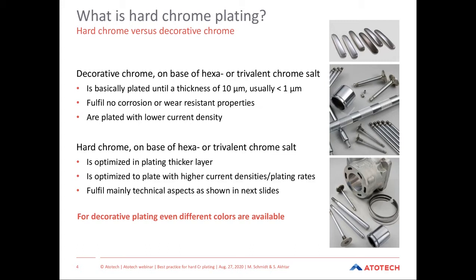Hard chrome, on the other hand, is plated to improve the lifetime of the component in service. It is usually plated to thicknesses ranging from 5 microns up to 300 microns, of course, depending on the application requirements, and in some rare cases, even higher than 300 microns are plated. The process is used at much higher temperature and cathode current densities compared to decorative plating. So these are the main differences between the two types of chrome plating.